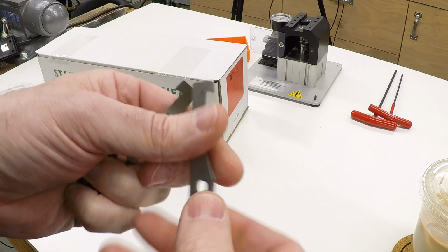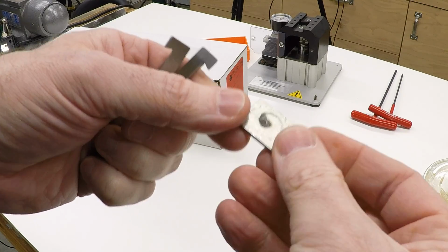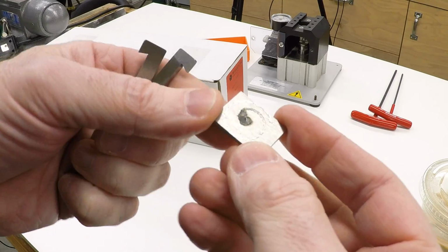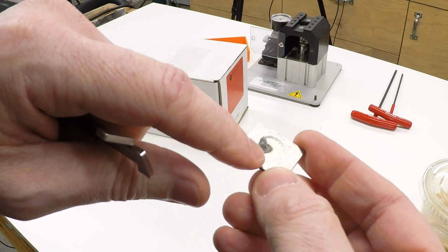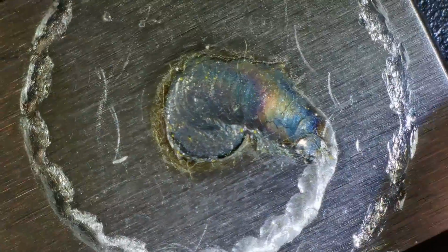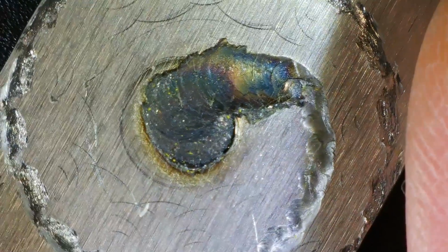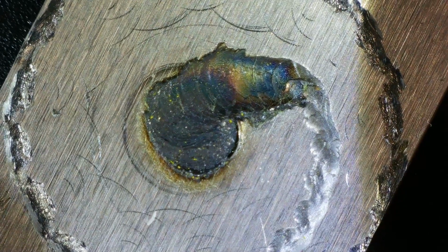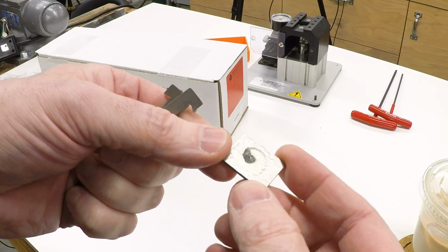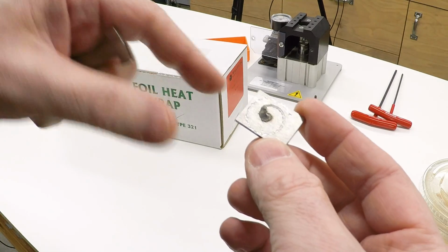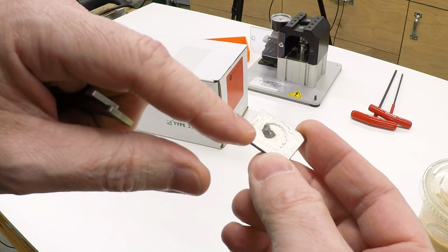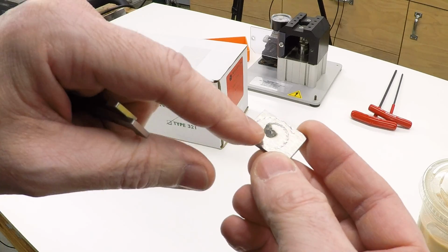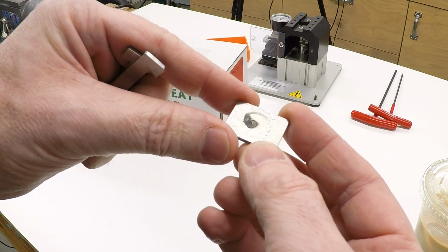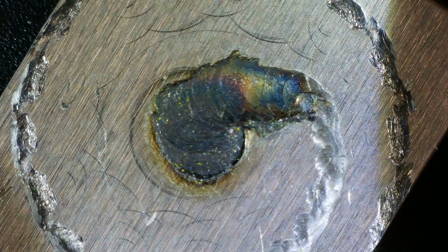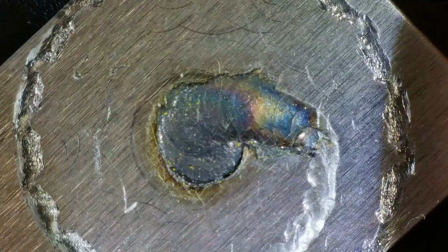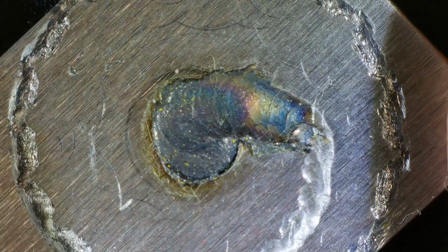I did have one mishap. If you may have seen this on Instagram. This is a little scrap of one of the parts. And what you see there embedded in that is an M42 Cobalt drill. I had it spinning at 6,000 RPM, started the CNC program, and it was the wrong code. I actually had the code from the recontour still loaded when I went to make the second part. And so it tried to plunge down thinking it was a short end mill, and it was not. It was a long drill, and it has embedded that drill, and actually it looks like partially liquefied it into there, and that is now a permanent part of this.